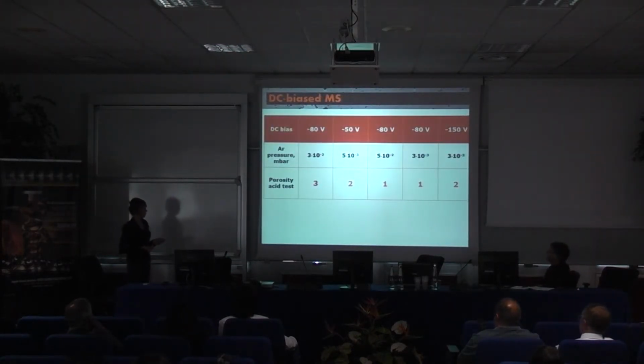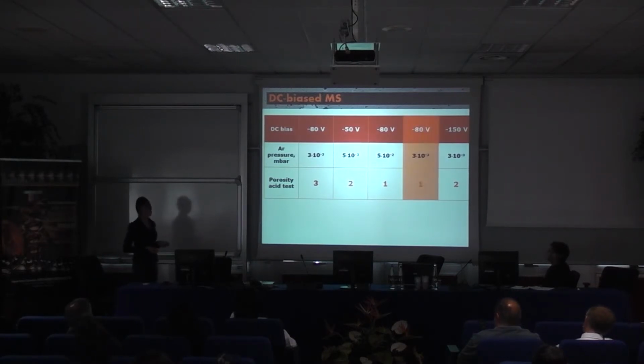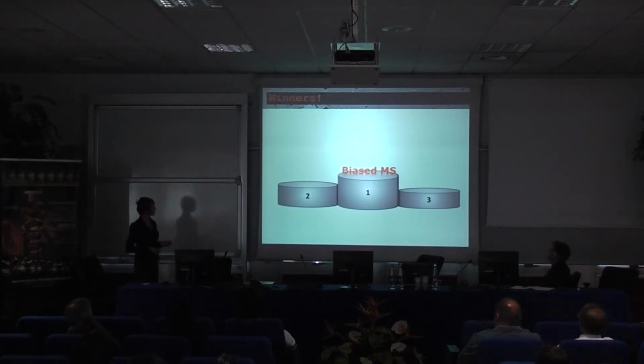DC biased magnetron sputtering has been found the most successful technique to decrease porosity of a film. We have investigated several bias voltages with a different pressure. Bias has been shown to influence more on porosity in a case of lower pressure, 10 to minus 3. And in any case is much lower than the standard samples. For one of the samples we have compared the data with the optical profilometry, and it has been found to be 0.1%. And also we have observed it with the scanning electron microscopy, and the film was found with minimal porosity, smooth and dense. So the winners of our race of techniques for films of minimal porosity is biased magnetron sputtering, deposition when the substrate is heated, and deposition of thick film.